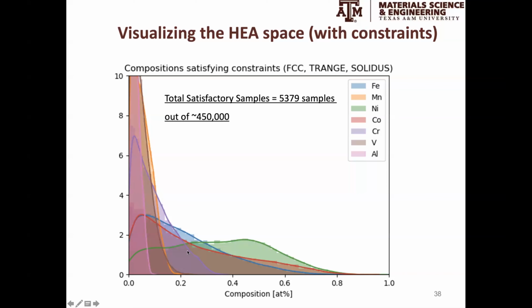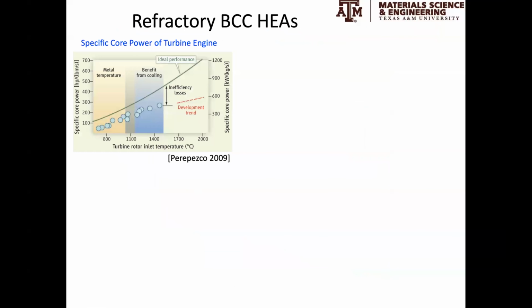On the other hand, we see that in this feasible alloy space, there is a wide range of possible nickel amounts in the solution to this alloy search problem. So in essence, by looking at these composition histogram plots, we can tell more or less what the chemical signature of the feasible region in this alloy space is.